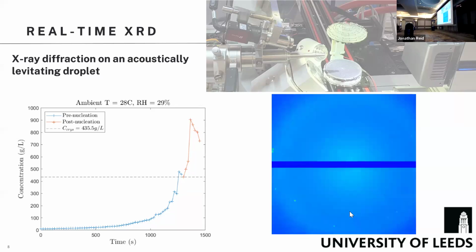Right, yes, that's a good point indeed. This is something that I've back calculated. I know the change in size of the droplet as it evaporates, and I also know the initial concentration, as this is something I've measured. So I've back calculated the concentration inside the droplet, but indeed this is the average concentration. And it is actually the case that the concentration of solute at the surface would be higher than at the center. So I could also try to feed this data directly into my model, which looks at diffusion of the salt, and try to see what was the concentration at the surface of the droplet. That's something I could do. Maybe get a better estimate of this critical concentration when crystallization starts happening.